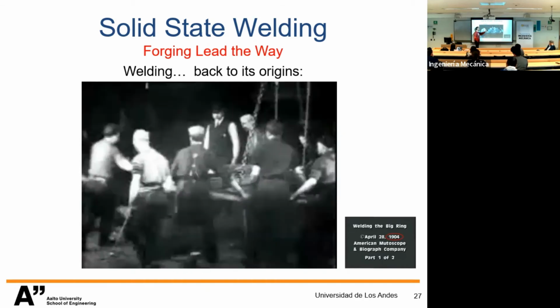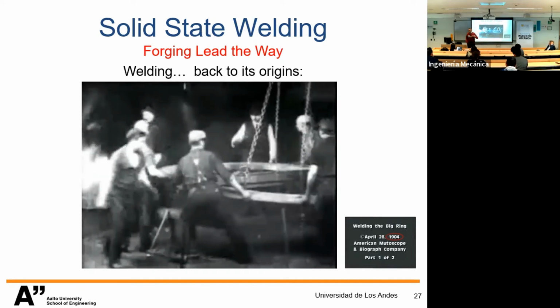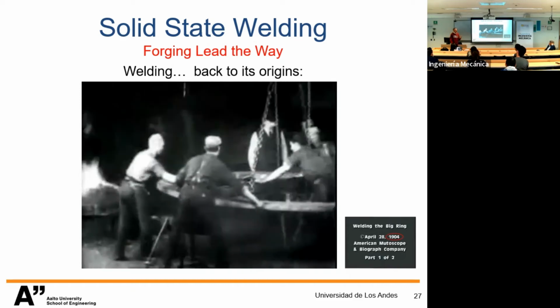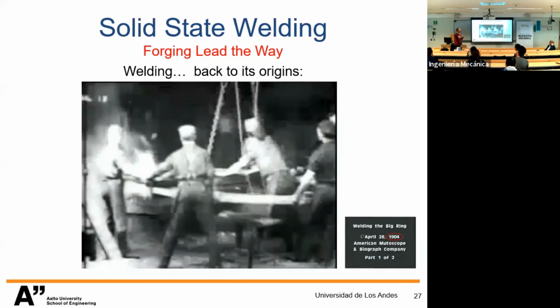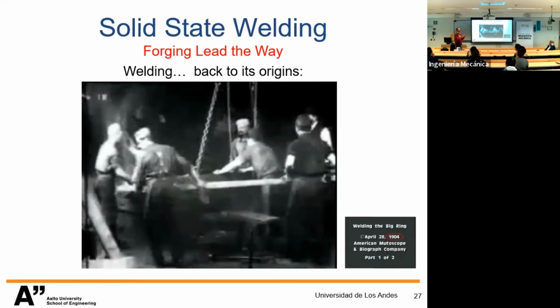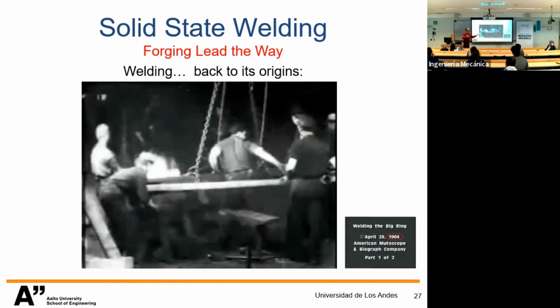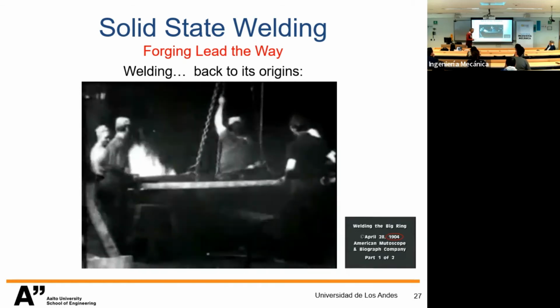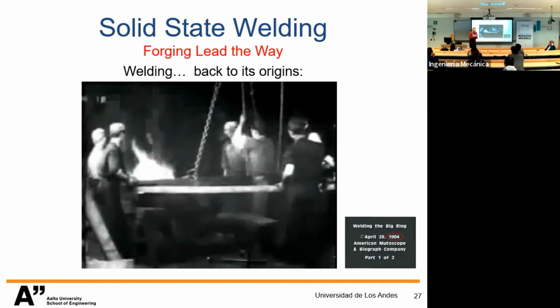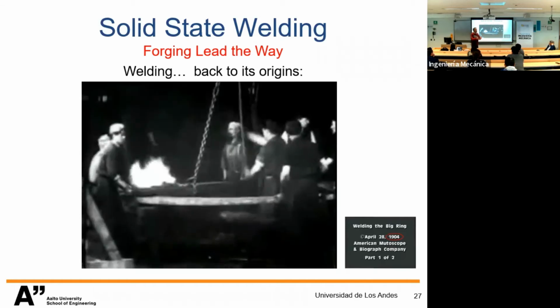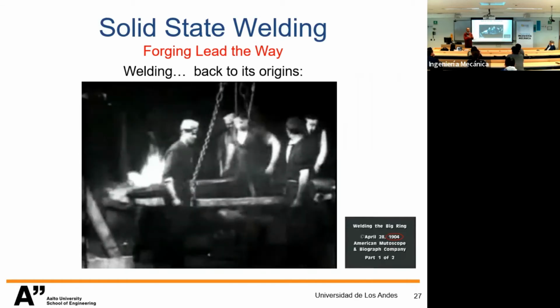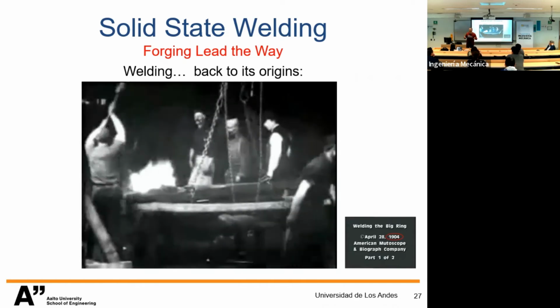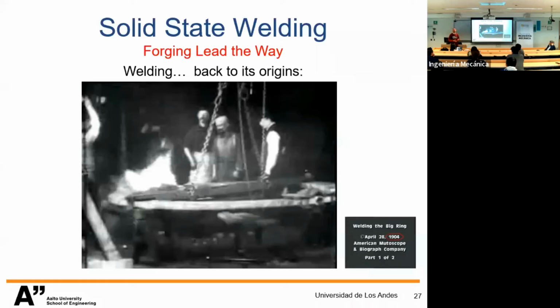Because these metallic components have properties that transmit the energy, so they are energy vectors also. And so if the power density is not able to promote an increase of temperature higher than the rate of transmission, by heat conductivity directly, but also heat capacity and mass, then the flow of energy overcomes the rate of energy that is introduced in the material. When you have the process at the point near melting, everything is melting. So it was not possible to process materials in fusion. We could only use brazing, where we have filler metal in fusion, but the base materials are in solid state, and therefore the mechanical resistance is low.